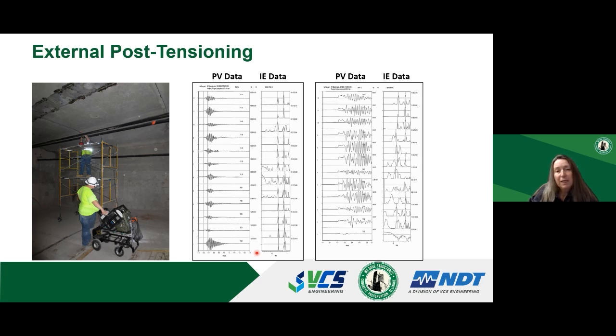So although our device collects the impact echo and pulse velocity data at the same time, for locating of grouting defects, we don't really use the pulse velocity data because it's looking at the velocity domain. We look at the impact echo data. The principle here is that the frequency with which the wave resonates in a concrete section is related to the thickness of the section. When we have an internal or an external tendon that is fully grouted, we will be measuring the frequency that corresponds to the true thickness of that element. So whether it's the true diameter of an external duct or the true thickness of the web or the deck for an internal tendon. So as you can see in the middle image, the impact echo data shows a very consistent frequency for all the measurements.